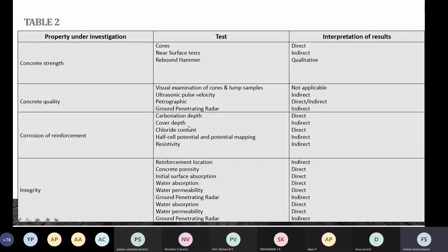Because cover depth is somehow important. If the cover is less, it's more exposed to the risk of corrosion. That way, cover makes it important. So we have instruments to find out the cover, like cover meter survey. We are doing it for all investigations. We are making cover meter also a part of the investigation because it's very important. Whenever a structure has very thin cover, it's more prone to the risk of corrosion.